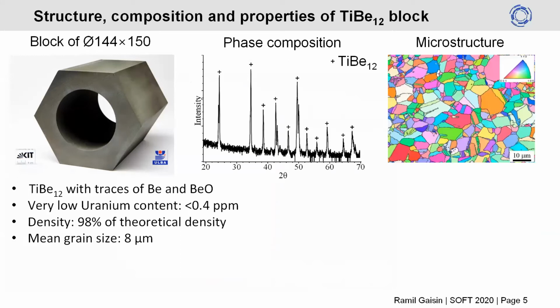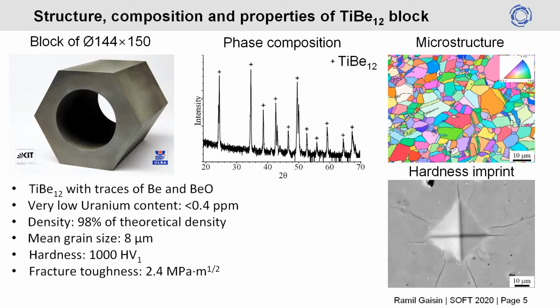The material has a very low uranium content. It's 500 times less than American beryllium, which means there won't be long-life isotopes after working in a fusion reactor. The obtained beryllide has a fairly high density, small grain size. It's a very hard material with a fracture toughness like many ceramics.